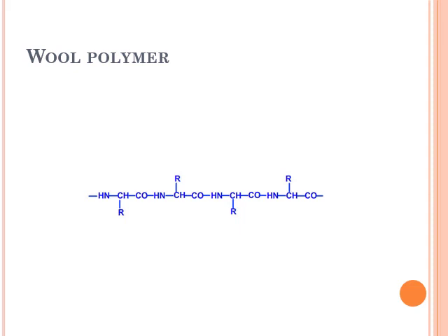In its normal relaxed state, the wool polymer has alpha keratin structure. Stretching of the wool fiber tends to straighten it into an unfolded configuration called beta keratin. A beta keratin wool polymer always tends to return to its relaxed alpha keratin structure. The wool polymer system is largely amorphous in nature, as it is only about 25 to 30% crystalline.